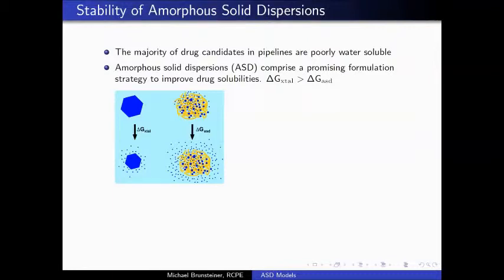And this amorphous API needs to be stabilized in some way or the other, because typically the amorphous form is less stable than the crystalline form. And if you wait some time, it's going to crystallize and you lose your solubility edge. So the idea is you embed your amorphous compound, which you can prepare in various ways, in a matrix made of synthetic organic polymers. And then it's simply better soluble many times.